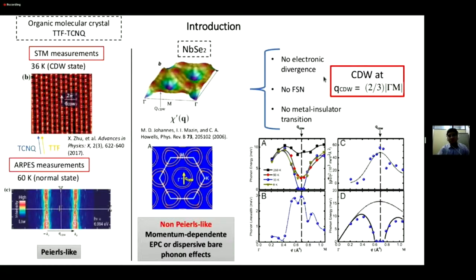We also have the formation of charge density wave for many other compounds, like, for instance, transition metal chalcogenides. For the transition metal chalcogenides, the history is a little bit more complicated, because for this kind of compounds we didn't see any electronic divergence, for instance, for the electronic susceptibility. We don't see any evidence for Fermi surface nesting. In some of them, we don't have a metal-insulator transition, even though we have a charge density wave. So it seems that this explanation for the occurrence of charge density wave given by Peierls is not the whole story. So there should be more behind it.